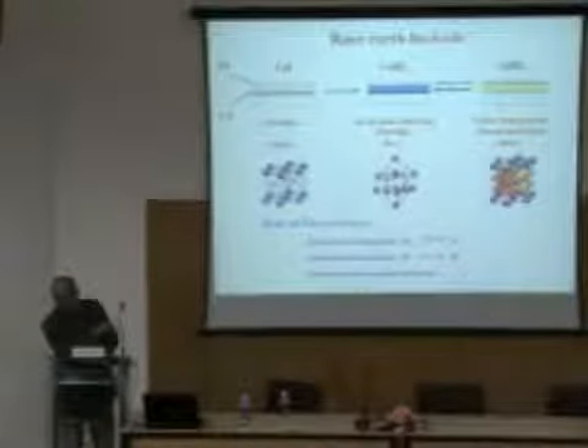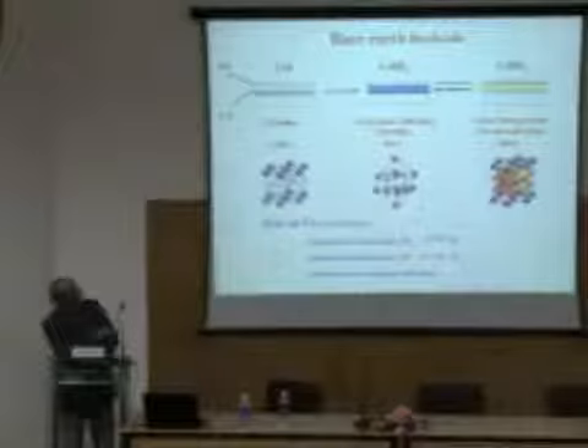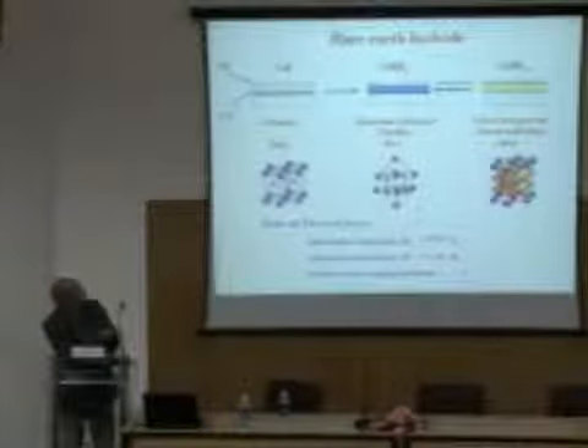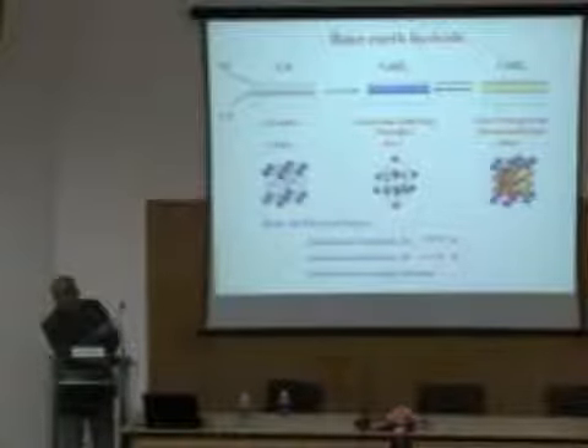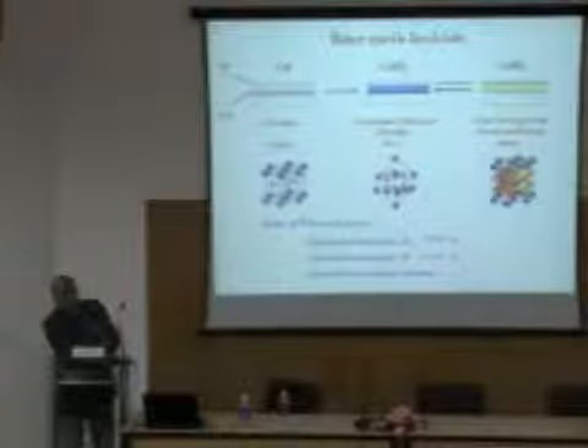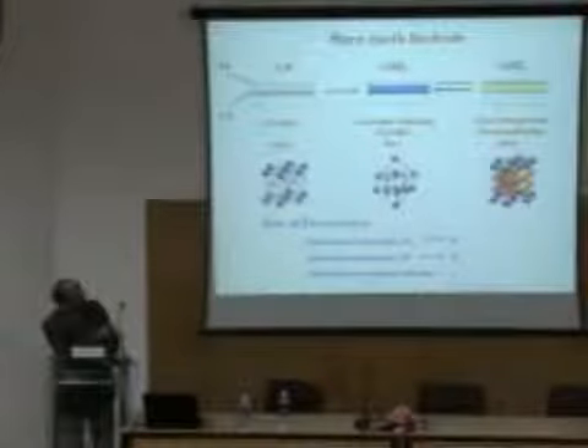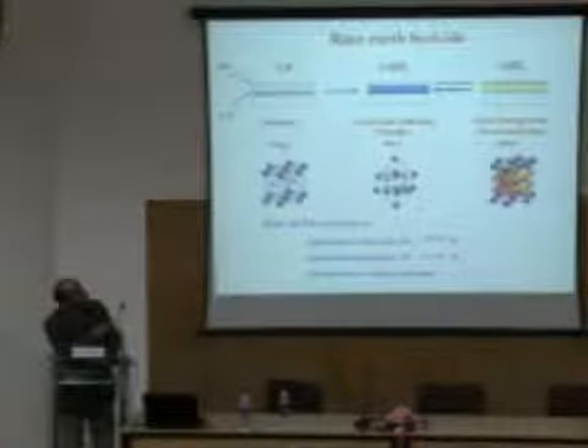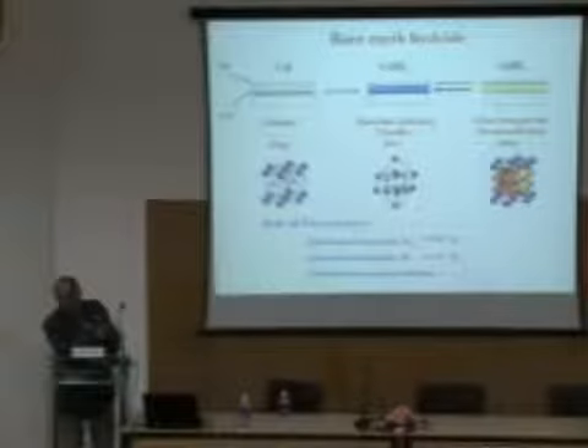What is interesting is that the crystal structure has changed as we go from metal to dihydride to trihydride. The electrical nature of the material has changed. It was metallic, it has become a semiconductor or insulator. Optically, it has changed. It was reflecting, here it has become transparent. Interesting thing is you can go back and forth. You can go from dihydride to trihydride. When you remove hydrogen, the material comes back to the dihydride state, and reversibly you can go back and forth. You cannot come back to the metallic state, but you can come back reversibly to the dihydride state. And you put in more hydrogen, again you can go back to the trihydride. So this is a reversible transformation.